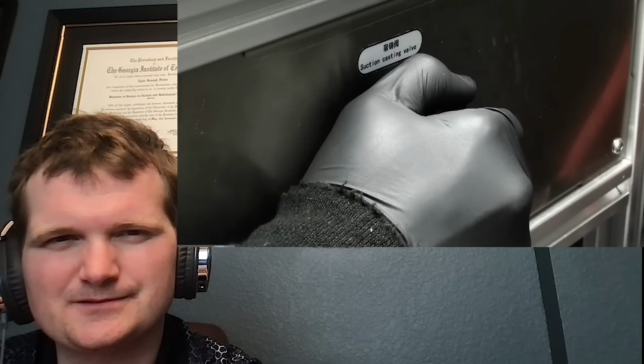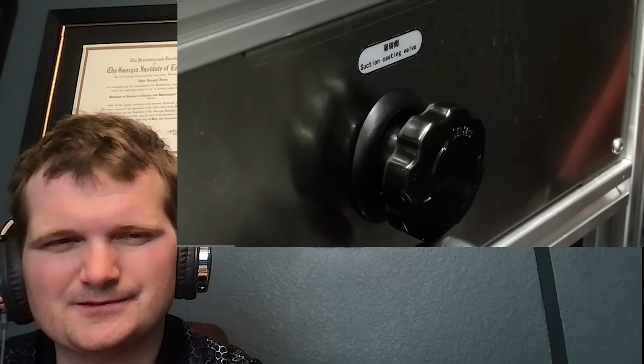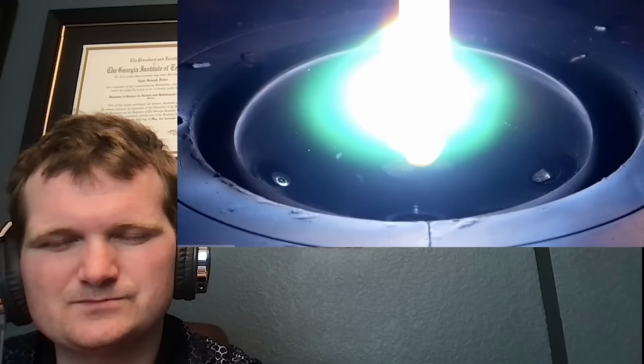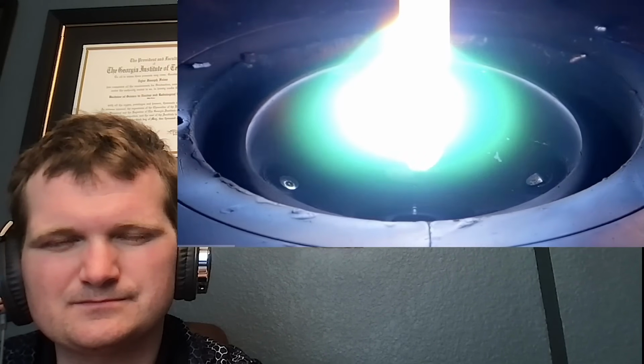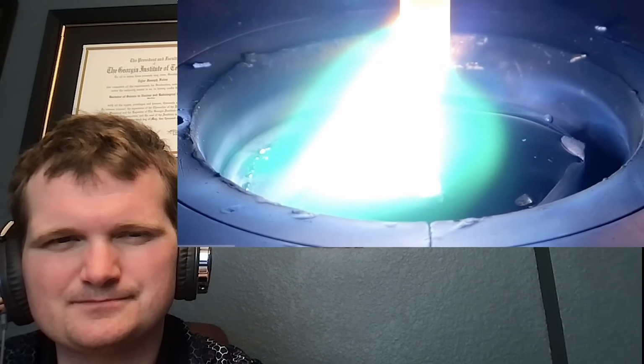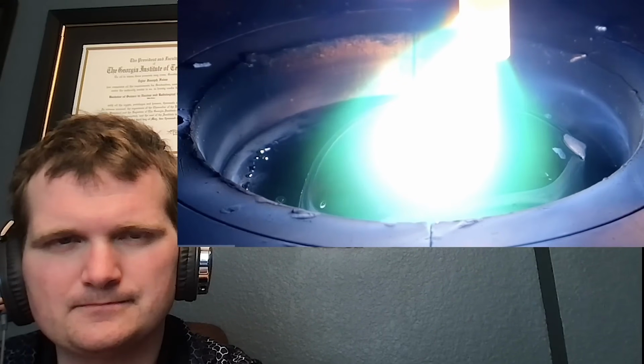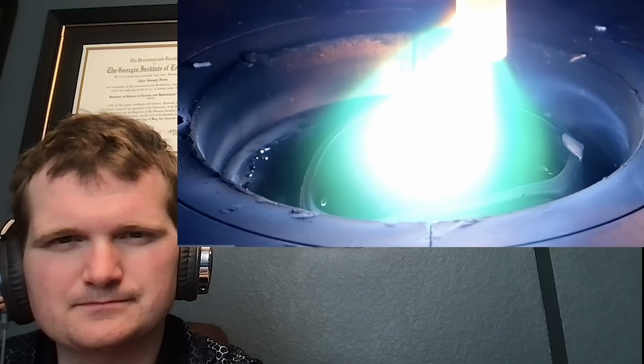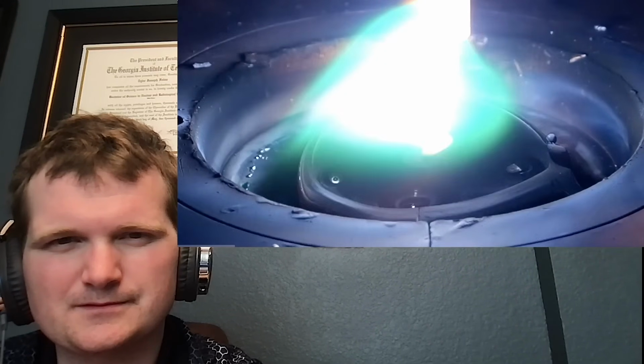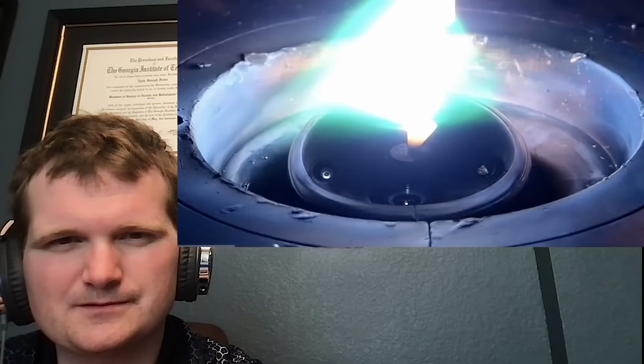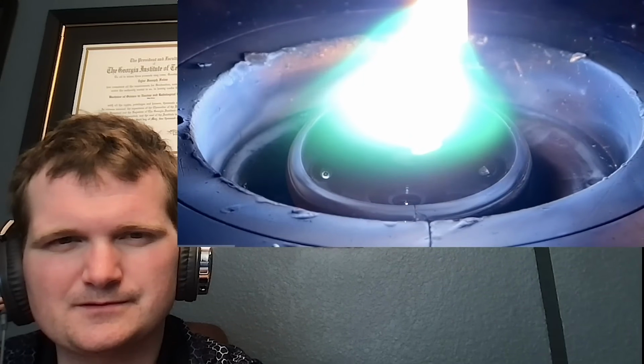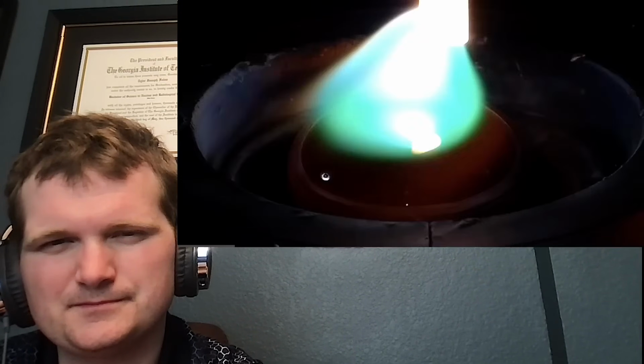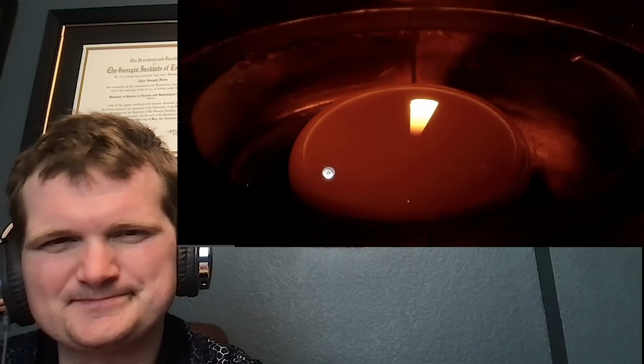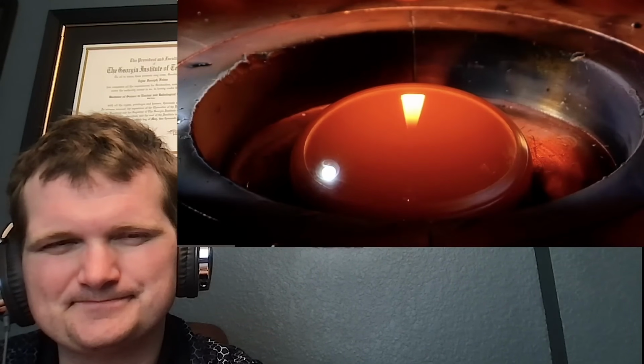I also had to do this slowly and very carefully, which I felt would help prevent the metal from just blasting through the mold, and almost right away, it all started getting sucked in. Then not long after, it started looking very similar to my other attempts, where there was just a small bead left at the top. The only difference this time was that the bead looked like it was slightly bigger, which kind of implied that it didn't all go in, but at the same time, I did start with a lot more metal, which made it hard to tell.